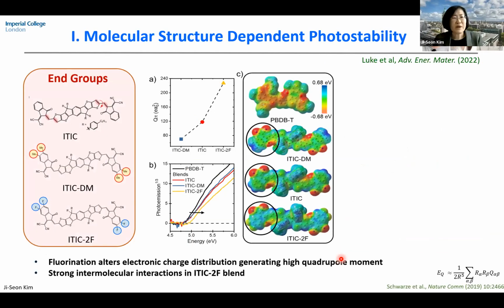It turns out that there is a very interesting molecular electrostatic potential we have to consider. Because the ITIC molecule has a very symmetric structure, in general NFAs have a very low dipole moment. However, when you change the donor and acceptor character by putting fluorine atoms, for example, you change the local charge distribution. Therefore, there is a strong impact on the quadrupole moment, particularly in the pi-pi stacking direction. When we calculate the quadrupole moment Q pi value, you can clearly see the strong dependence on end groups. And this Q pi value is very important because it determines the very close intermolecular interaction between NFA molecules, and also between NFA and donor polymer molecules in the blend.